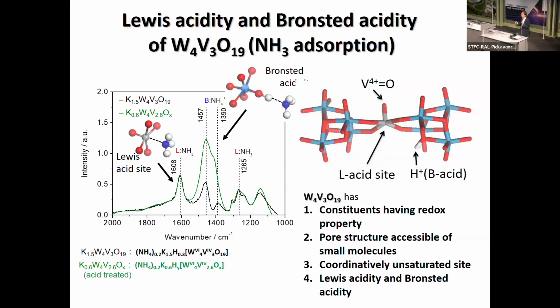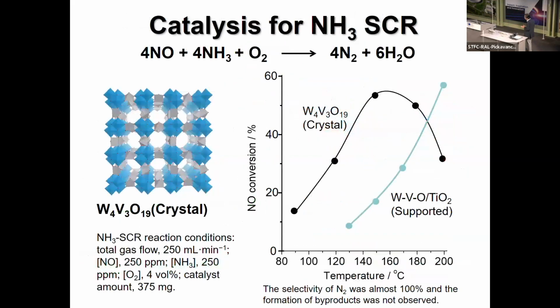So in this case, I have to remind you the material doesn't need to be activated by high temperature treatment. This material directly shows catalytic activities. In fact, we use these materials for ammonia SCR reactions. The data is shown here. These materials show much higher activity working at low working temperature. If you compare to the industrial type catalyst, which is supported on titania, well, it's a good catalyst, but our catalyst is much superior to this.